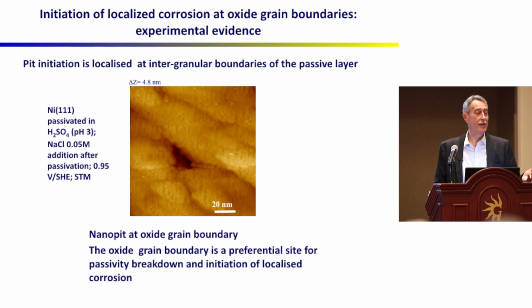So it's completely in line with the local density of states measurements, which have shown that there are more oxygen vacancies, so that these points are more reactive towards chlorides. And I think that I will stop here. I don't think I need a conclusion. If I should make a conclusion, it would be very short.